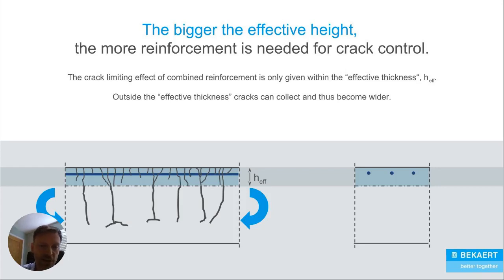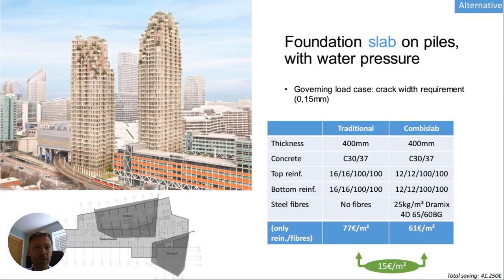Important thing to note is that if you're going to design an industrial floor to a crack width, the higher the effective height of the concrete, so the thicker the slab is due to loads designed in the ultimate limit state, the more difficult it is to get that defined crack width calculation. Okay, so thinner slabs in general need less reinforcement, be it steel and rebar, than you would need in a thicker section in order to achieve the required crack width that a client needs. Very important to know.